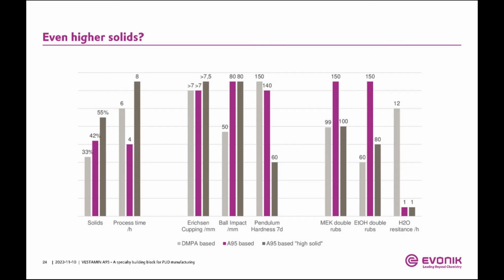The cupping and ball impact, of course, are very fine. Again, these are reflecting your flexibility. Of course, this is convincing, right? If you choose a more flexible building block, you should not expect to suffer in the flexibility, but the pendulum hardness, of course, goes down. If you choose to go for highly flexible molecules, this is also not surprising. Mechanical property-wise, we are very close again to the original DMPA status. So I would say it's still okay, just a little bit lower than with the original 1000 polyester.